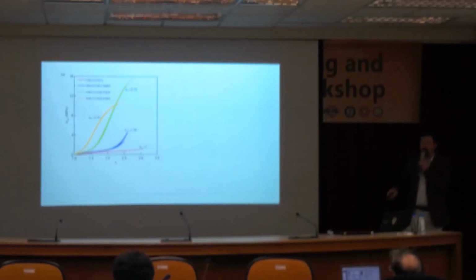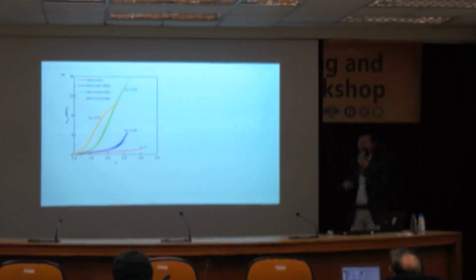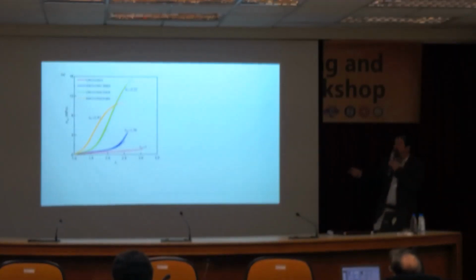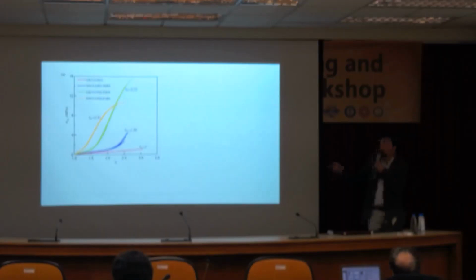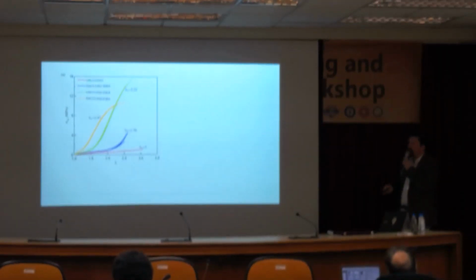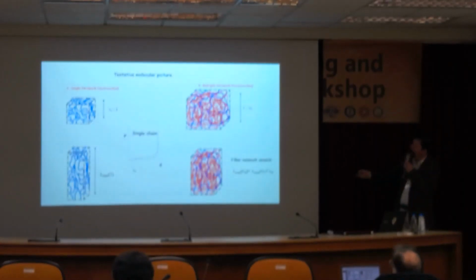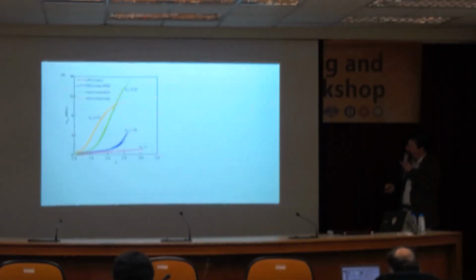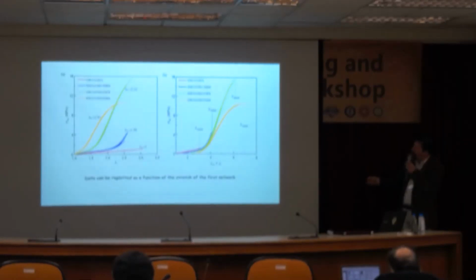This is actually exactly what you have in your tires. The rubber that is used in the tire is filled with nanoparticles. They do exactly this. If you have nanoparticles, the extensibility doesn't change, but the stress increases. Now, how can we understand this? If we try to renormalize things by the first network stretch, so you see these materials are all made from the same initial sample, this one. You start from this, and you do swelling at different levels of swelling. Now, let's renormalize the data by our lambda, the experimental one, times the pre-stretch.